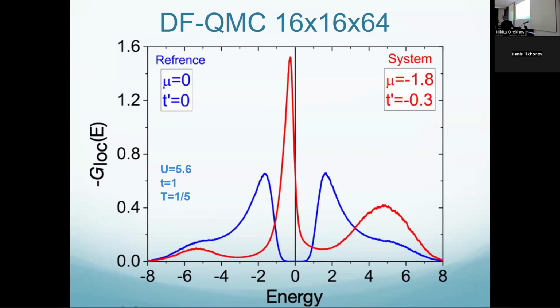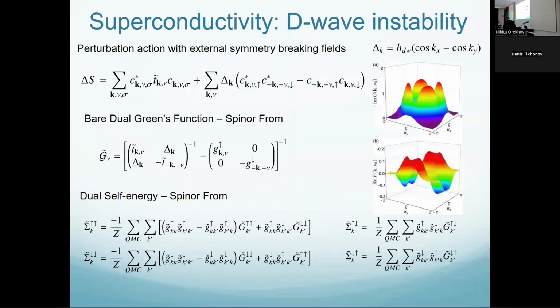So you see what we did, we shift this to this peak. And suddenly this peak goes close to the Fermi level and becomes extremely sharp. I will explain why. It's very good for superconductivity when you have some big states near the Fermi level, but this Hubbard band almost stays the same. And moreover, we can now understand superconductivity.